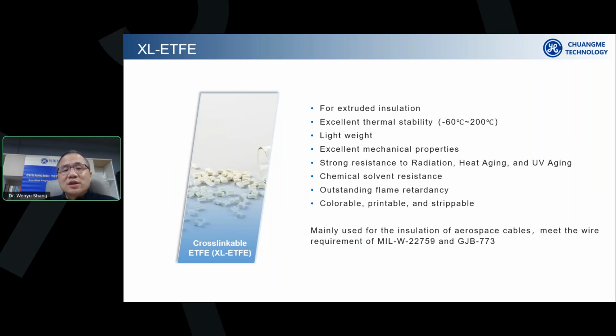As you can see on the second line, I also mentioned previously that this cable needs to sustain very low temperatures, down to -60 degrees C, and very high temperatures up to 200 degrees C. So this is a very wide temperature range the cable needs to work in on airplanes, missiles, rockets, satellites, and similar application areas.